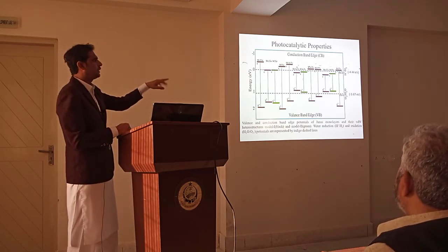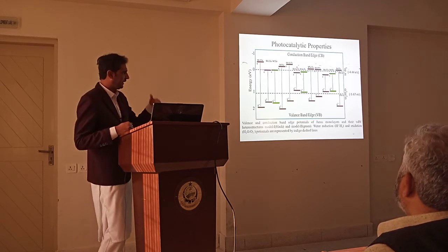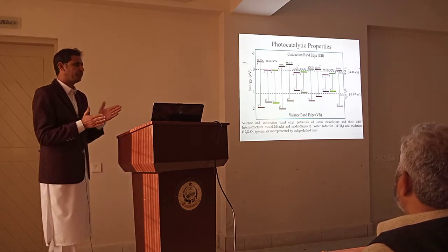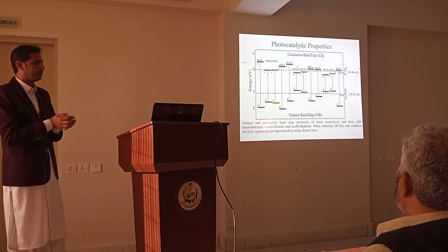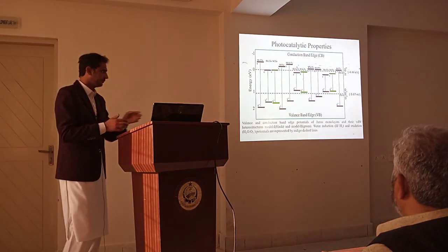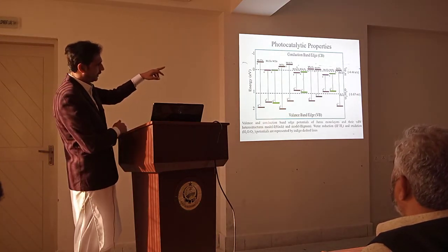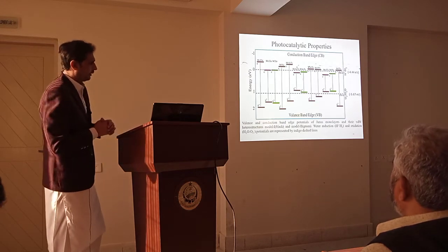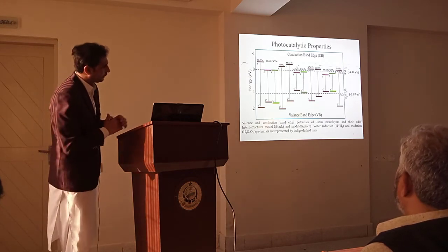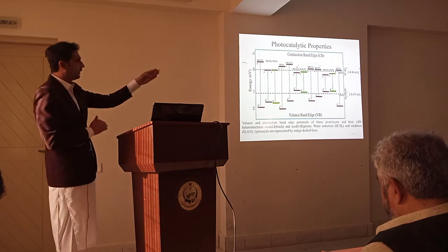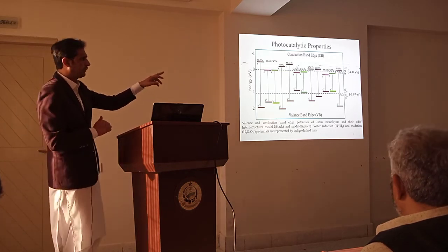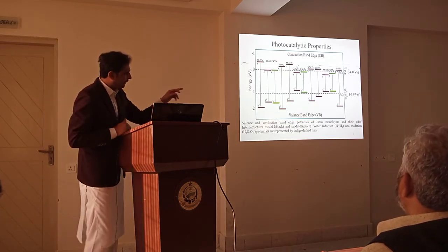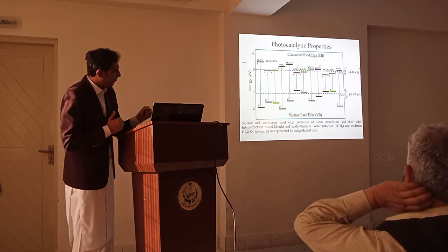Here the indigo lines represent the redox potential. When a material crosses these redox potentials, it means that these materials will be best for photocatalytic water splitting. The upper indigo line represents the reduction, while the lower one represents the oxidation process. I also mentioned their values: minus 4.44 for reduction, while minus 5.67 is for oxidation.